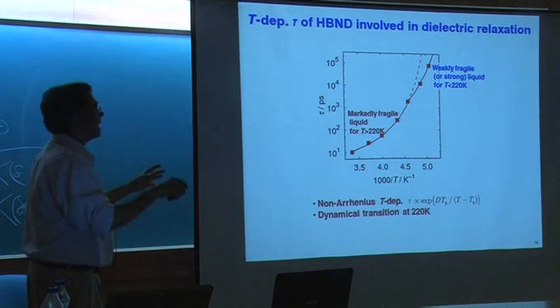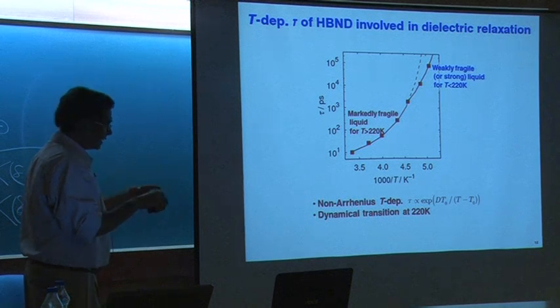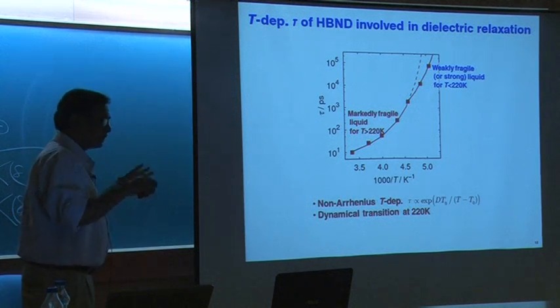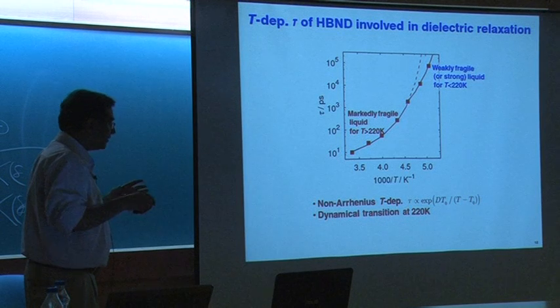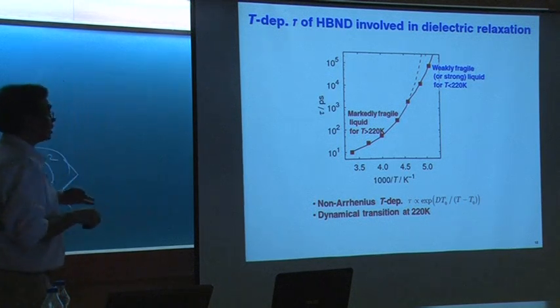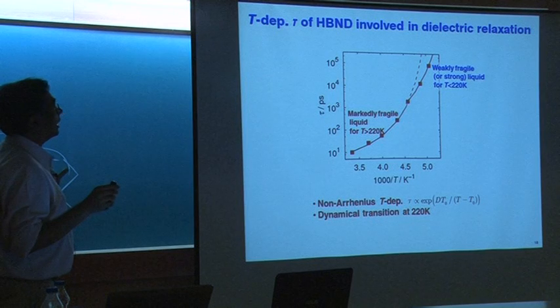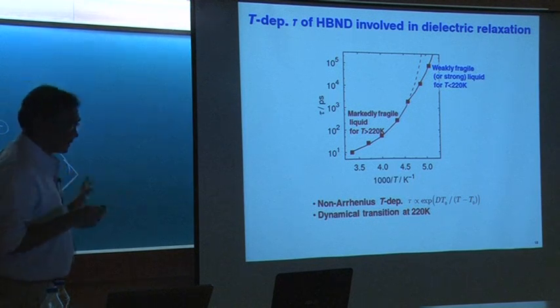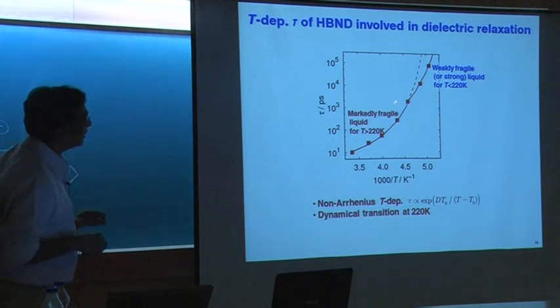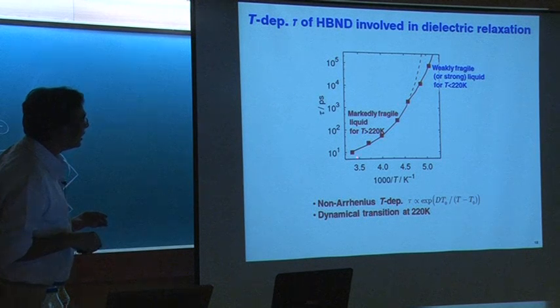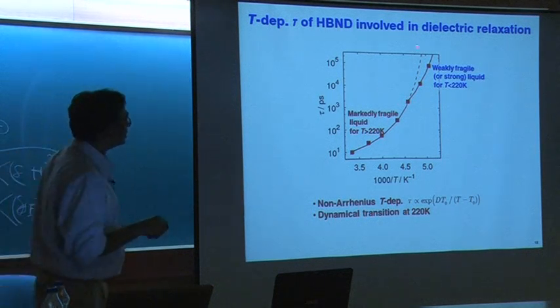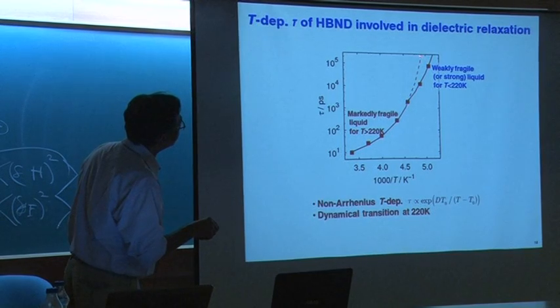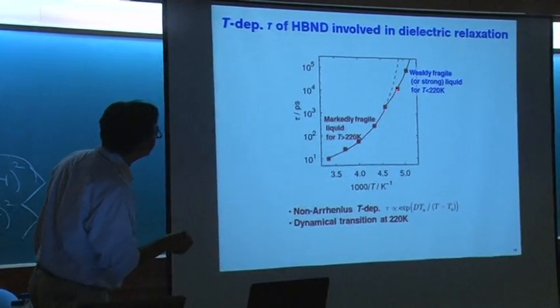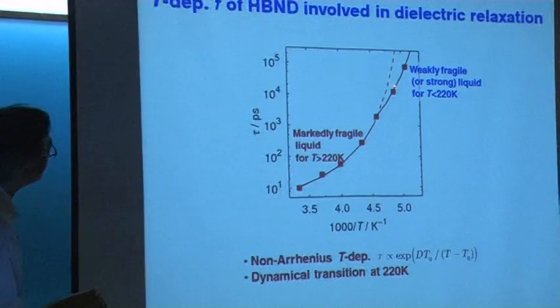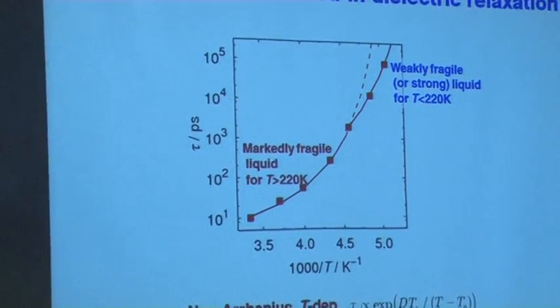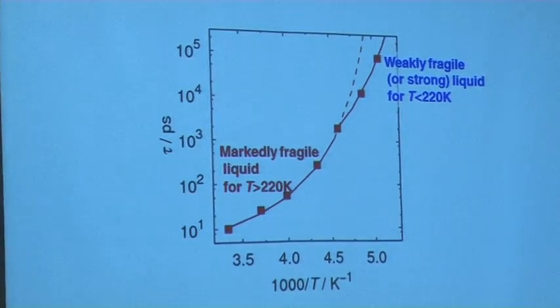Very rapidly, at a certain temperature, 30 degrees centigrade below the glass transition, viscosity starts to increase rapidly, relaxation time starts to grow, and it just goes to glass. After that it doesn't move. Not water. Water escapes the glass transition. Had it been here, relaxation time would have been much larger, about 2 orders of magnitude larger at this temperature. This is a logarithmic scale.